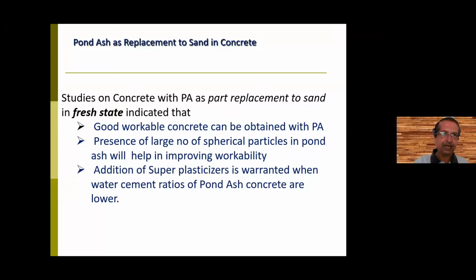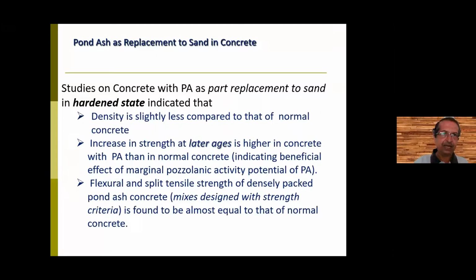The presence of a large number of spherical particles in pond ash improves workability. Addition of superplasticizers was warranted sometimes, when the workability was slightly less. Now, in the hardened state, density was found to be slightly less. Strength gain at a later stage was higher for concrete with pond ash compared to normal concrete.